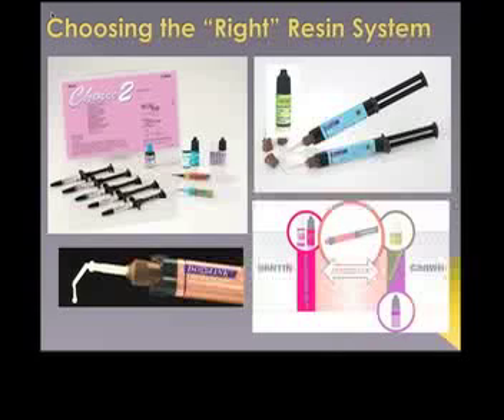The effect of acid monomers in self-adhesive cements causes cements to be weaker, more hydrophilic, and with lower bonds than adhesive resin cements. So the dual cure conversion and compatibility to corresponding adhesive primers differentiate cements in the marketplace and cause a significant challenge in clinical dentistry.